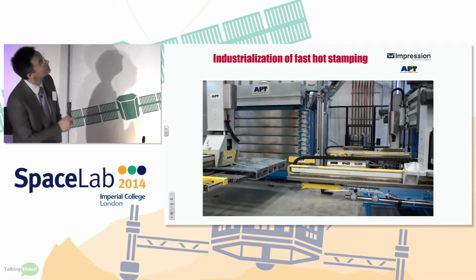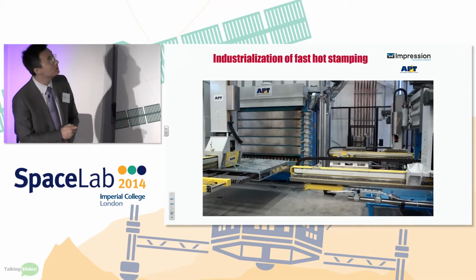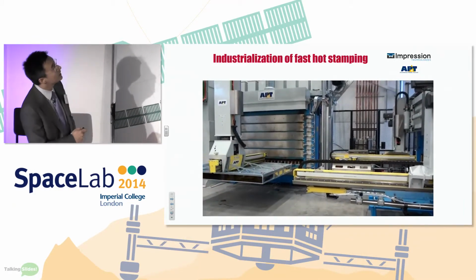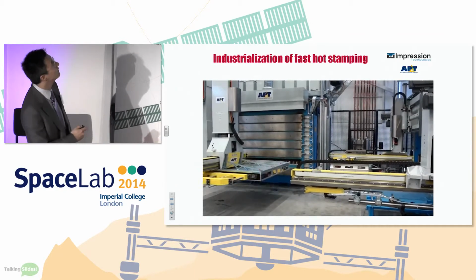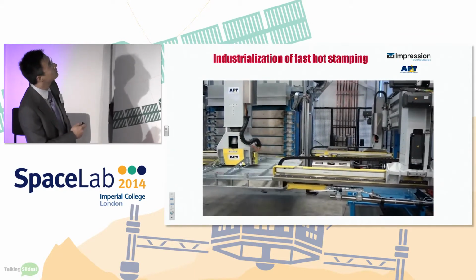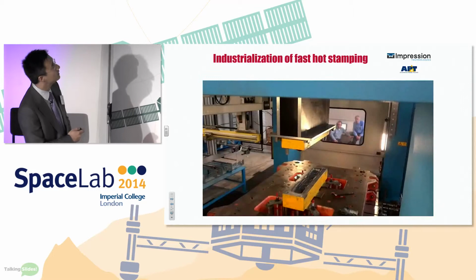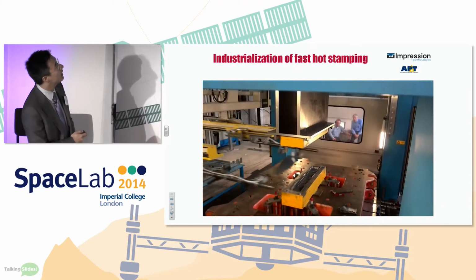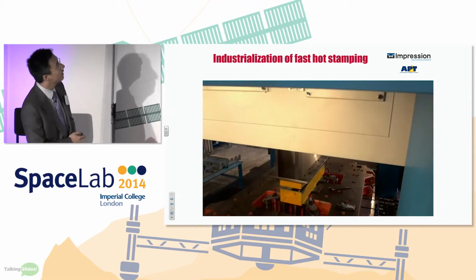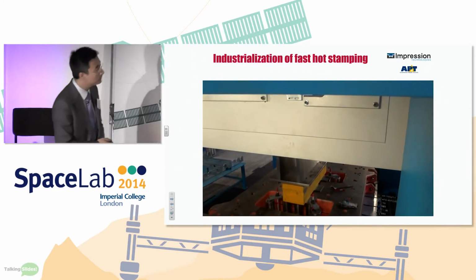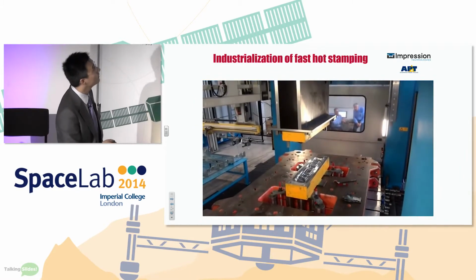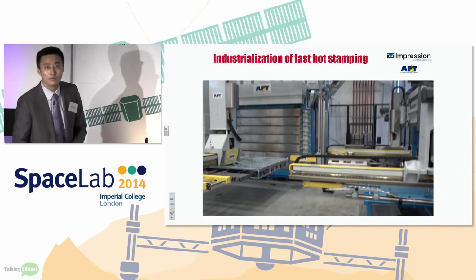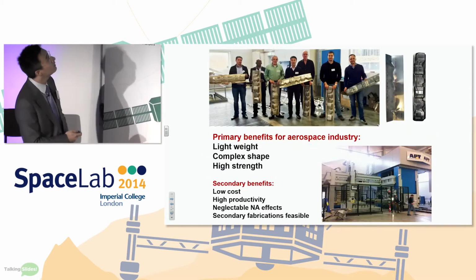So this is their latest model of the furnace, which is a multi-layer furnace, which can be controlled independently. So the hot blank was brought out by the speed feeder, put into the cold die, and formed very quickly. So the part can be formed very successfully.